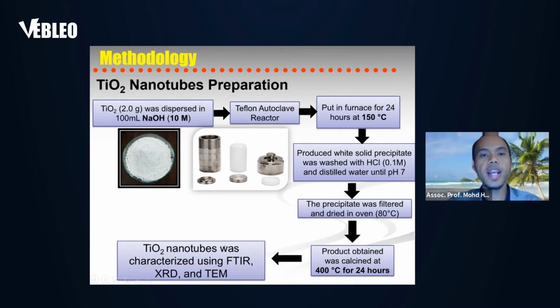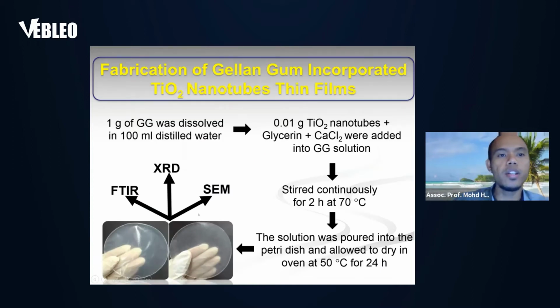Next, we incorporate the titanium dioxide nanotubes into gellan gum. 1 gram of gellan gum is dissolved in 100 ml distilled water, and then we add 0.01 gram of the prepared titanium dioxide nanotubes, glycerin, and CaCl2 to the GG solution. For information, glycerin and CaCl2 act as plasticizers to produce this film. The solution is then poured into a petri dish and put in an oven for 24 hours to produce this very nice film. That film will be characterized using FTIR, XRD, and SEM for its physical and chemical characterization.